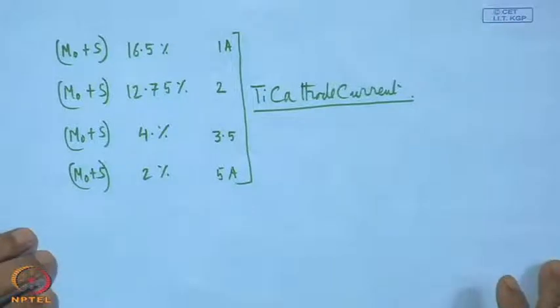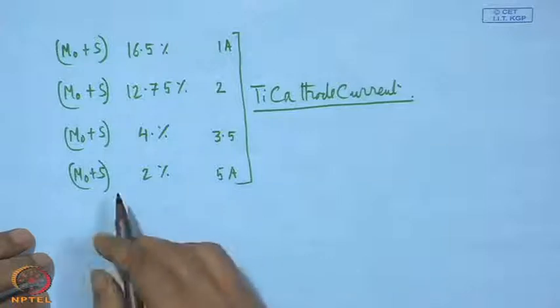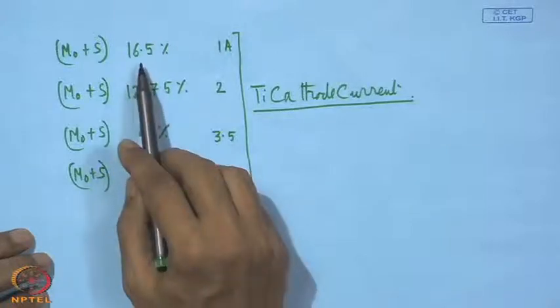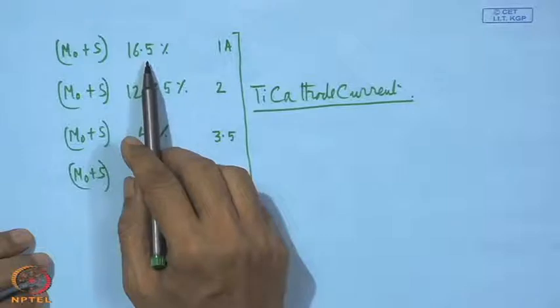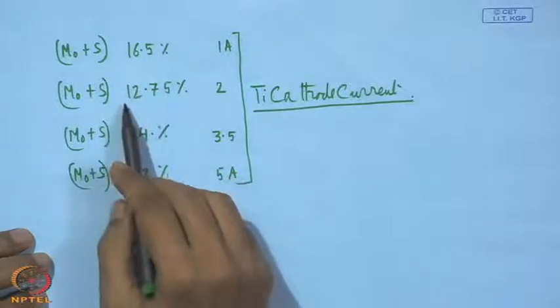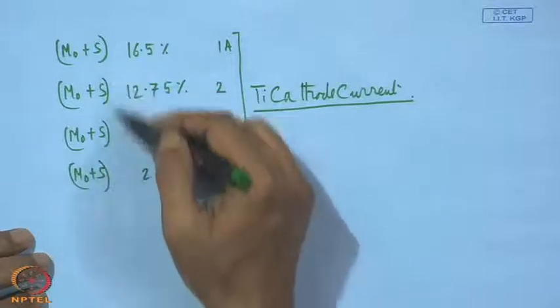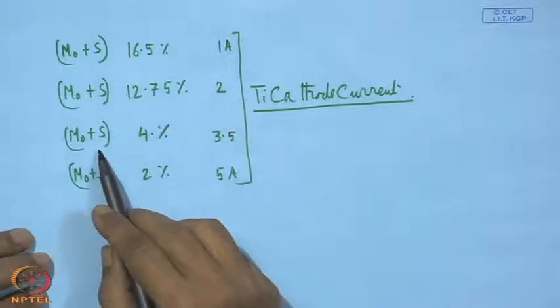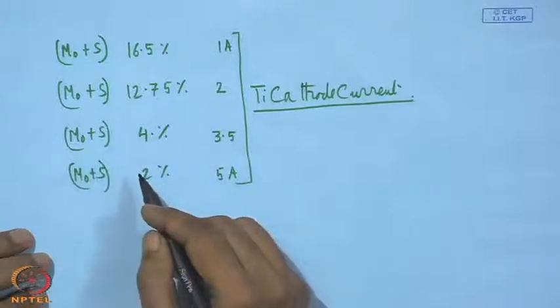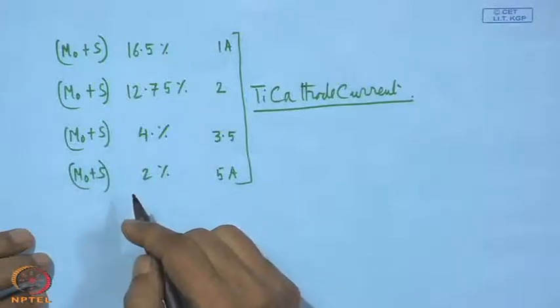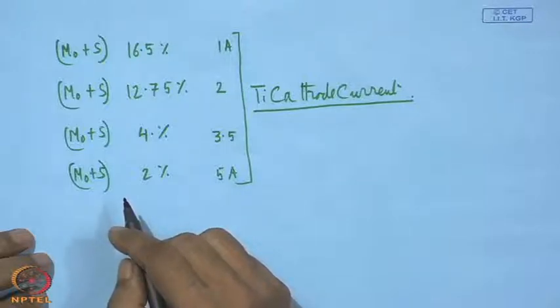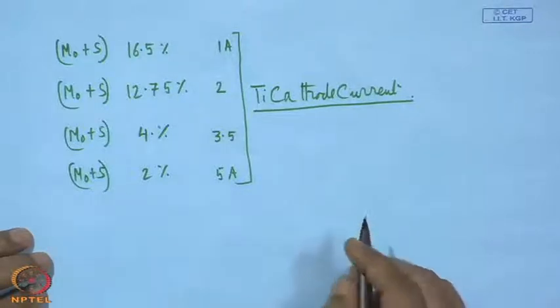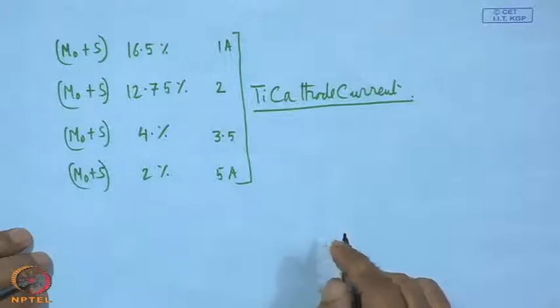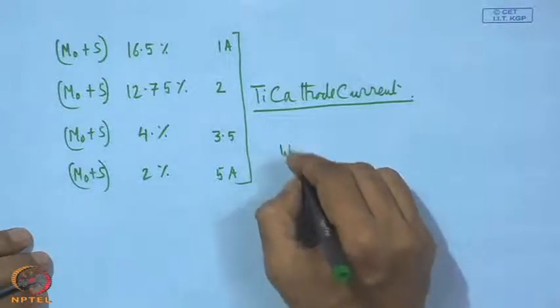Titanium cathode current. So, with this what we see is that the friction coefficient for this one is going to be the lowest, followed by this composition. So, the lower the value of MoS, the higher will be the coefficient of friction. However, what is very important to know here is that in this case we have also another term which we call wear coefficient.